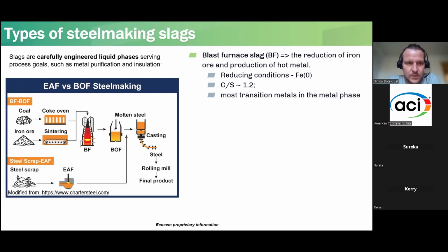So we take coal and iron ore, put it into a blast furnace, get hot metal out of it, oxidize the carbon out in the basic oxygen furnace, and then have the steel. And we regard steel scrap recycling and electric arc furnace slags a bit secondary. In the US, the proportion is exactly the inverse.